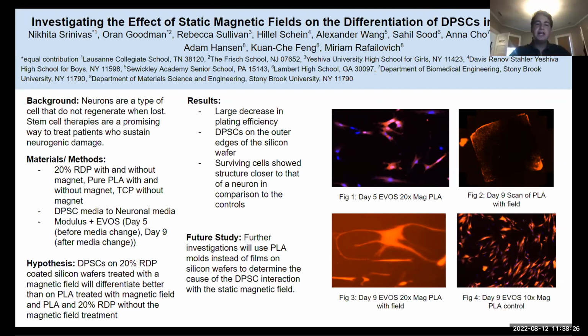So the day 5 and day 9 EVOS for the PLA inside the field seem to be differentiating very well. But interestingly, after day 9, our samples grown on the spun cast silicon started dying. This was weird, but in the end, we think that the electric charge produced by the semiconductive silicon under the magnetic field was the thing that killed the cells on top of it.